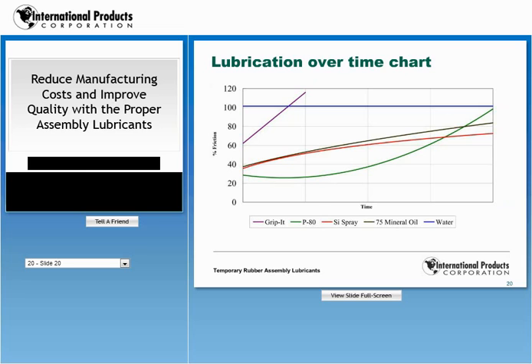Well, if you look at this next chart, it explains why. If you look at the blue line going across the 100% friction value, that corresponds to water used as an assembly lubricant. So again, if we go back to the example of putting the tire on the rim, even if you wet the tire before you do the assembly, it still requires 100 pounds to accomplish that assembly. If you look at the green line down at the bottom of the chart, that corresponds to a line of ester-based products known as P80. That reduces the friction to only about 30 pounds.